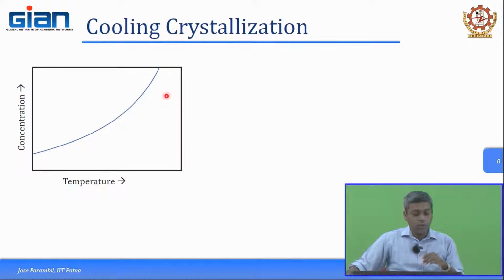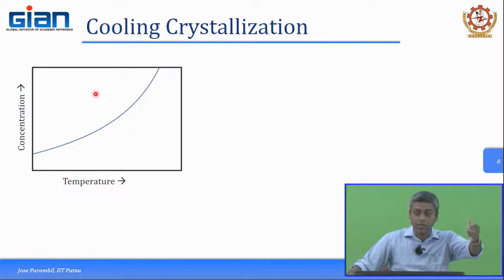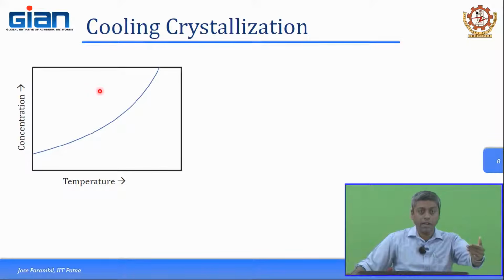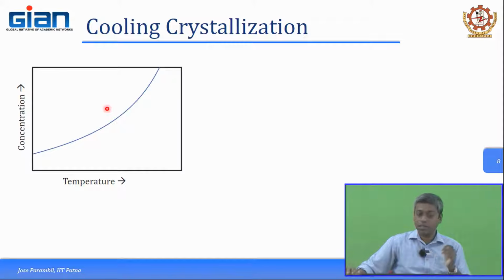As you move, what is happening is, let us say this is your 35 degrees Celsius here, you start moving along this line, and it would move up to a particular point where it starts crystallizing. So, it would move into the supersaturated region. At some point it would start nucleating a new crystal, and once the nucleation starts, then the concentration of the solution starts to come down, because the proteins are now moving into the solid phase. So, the liquid phase concentration comes down.